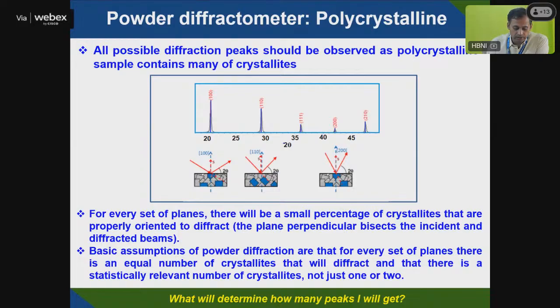You can see here that this blue plane, which we have marked, this 100 plane, is diffracting here. The 2 theta equation is satisfied, so we are getting a peak. Again, 110 is rotated sideways; another crystal is matching with 110, so you are getting that peak. Similarly in this case, 200, you are getting a peak. So multiple peaks you are able to see.